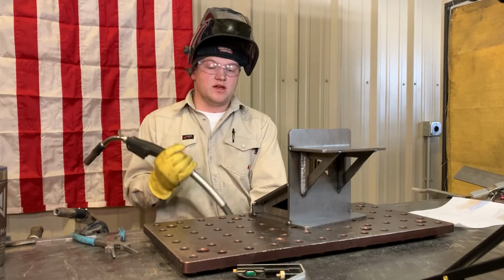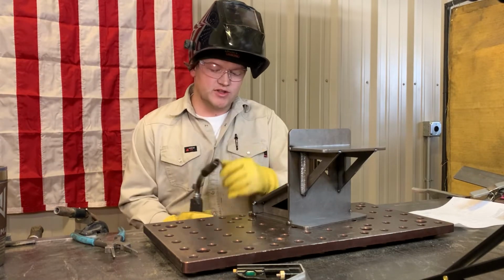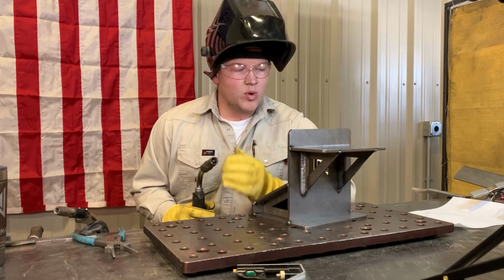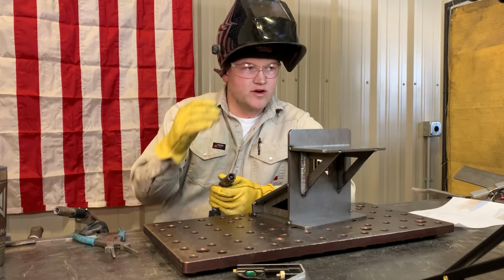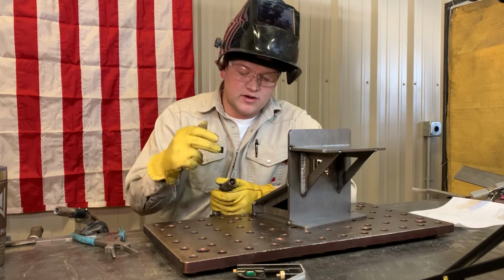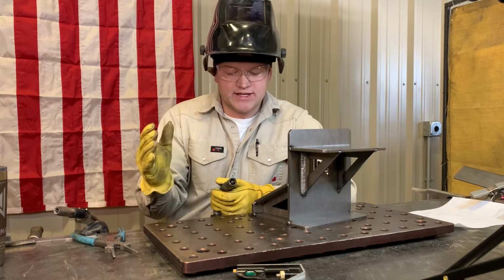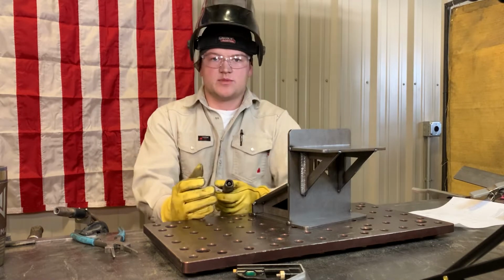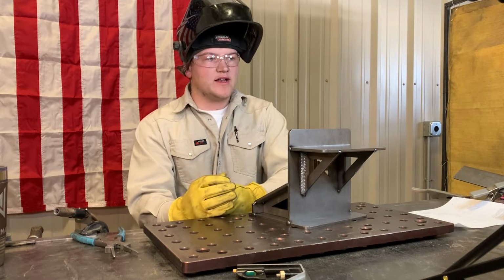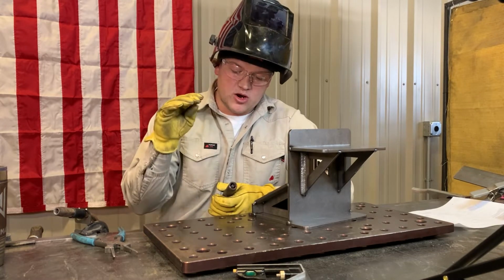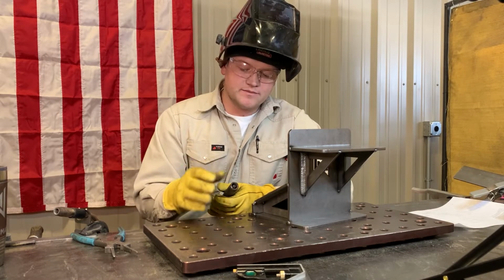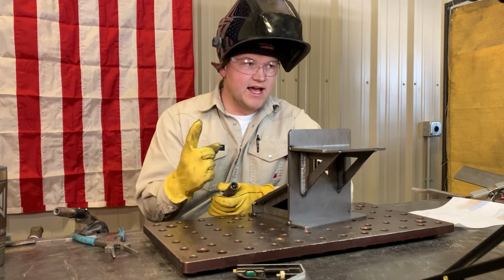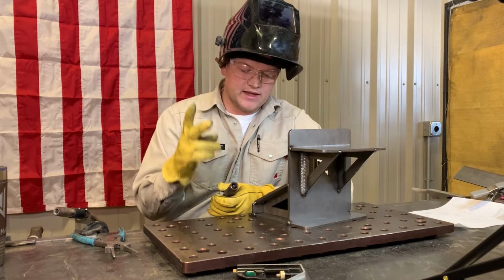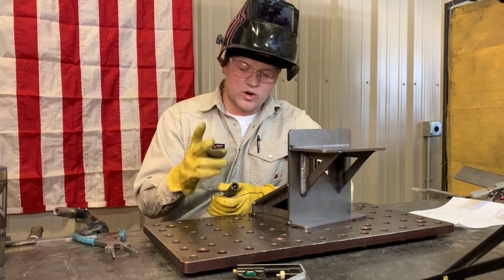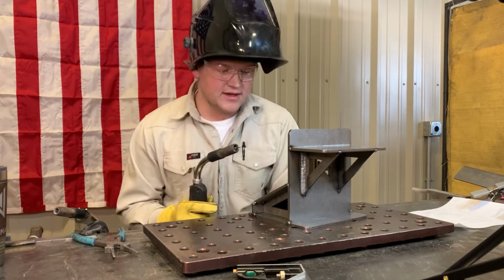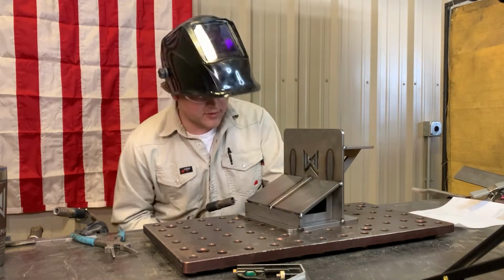Reason number 2 is the contact tip. The contact tip is literally the point of contact where the electricity is transferred from the welding machine to your wire. Right here at this contact tip is where that transition occurs. So if that contact tip is worn out, if the hole in it is bigger than the wire, then it's going to have poor contact, and the arc voltage is going to vary as you weld. So two of the biggest things are a clean gas nozzle and a contact tip that is in shape and not worn out. That will help your weldability a ton. All right, I'm going to start with these vertical pieces.